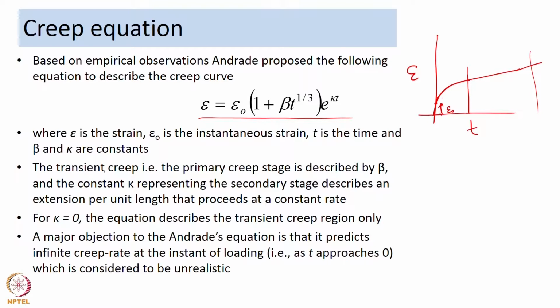Now, in his equation, the transient creep, that is the primary creep stage, is described by the constant beta, and the constant k or kappa represents the secondary creep stage, which is basically extension per unit length that proceeds at a constant rate. And if kappa is equal to 0, then the curve will be limited only up to stage 1, or only up to the primary or transient creep region.